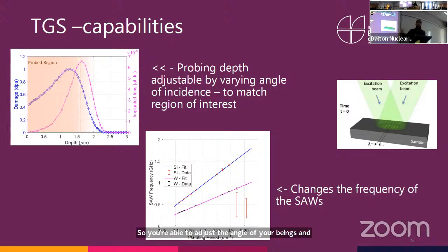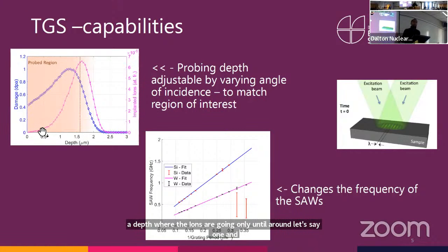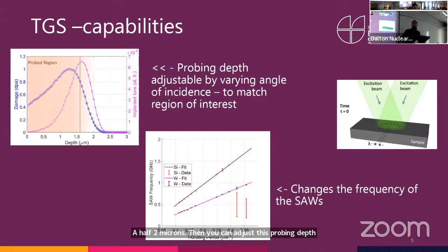So if you have a sample that has been ion implanted with a depth where the ions go in only till around, let's say, 1.5 to 2 microns, then you can adjust this probing depth for that region. That's the motivation behind going for this method, because when you use ion implanted samples, you have this very thin ion implanted layer.